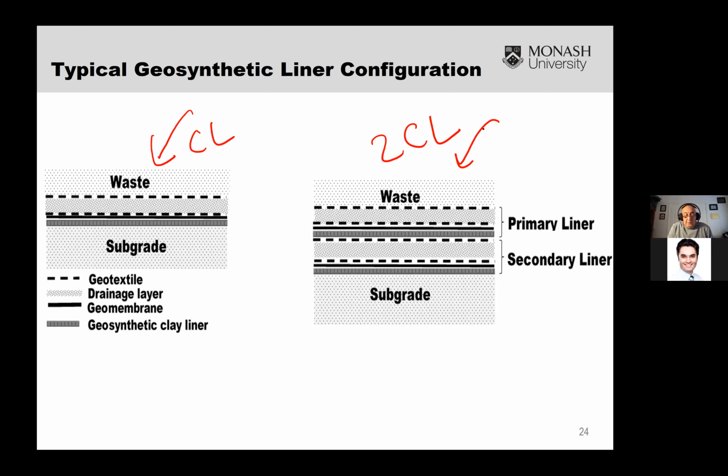You also know that migration of contaminants through a geomembrane free of defects is usually limited to contaminants that can partition and diffuse into the polymer comprising the geomembrane. This means that it is restricted to contaminants of an organic nature.